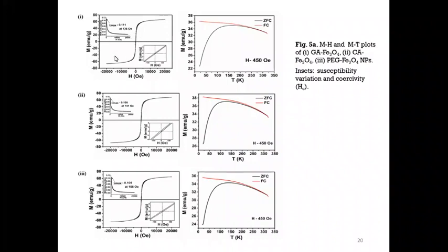Fine. So we are getting the higher saturation still, which is good enough. The saturation magnetization is good enough, and this is the M-T curve, the magnetization versus temperature, to check whether it is superparamagnetic at room temperature or not. So around 300 Kelvin, it is almost superparamagnetic.